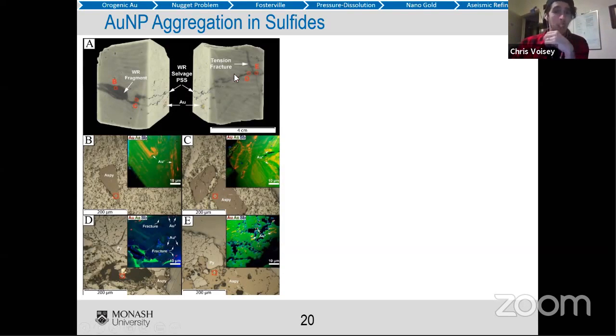So I took this sample here and I subsampled it into B, C, D, and E here, which correlate to these diagrams down here. This is the same piece of rock. I've just rotated it so you can see both sides. So this chunk of rock here, which is pretty much not pressure dissolved, is actually this same piece of rock here on the other side, which has become very pressure dissolved. And then we did NanoSIMS on it to look at the texture of the sulfide, and then how does gold